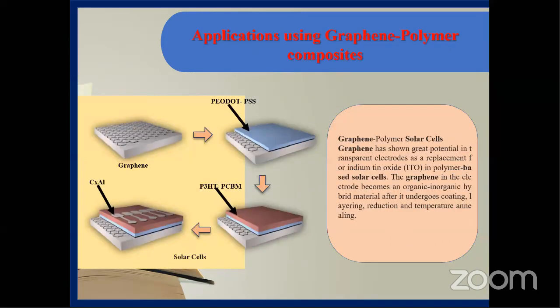And application using graphene polymer composite, it can be used for solar cell application. It is a replacement for indium tin oxide in the polymer-based solar cell. The graphene in the electrode becomes an organic inorganic hybrid material after it undergoes the coating, layering, reduction, and temperature annealing. So this is a potential application for these solar cells.